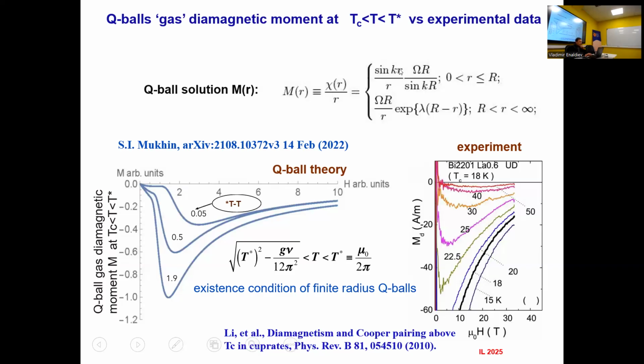How about coordinate dependence? Yes, indeed. If you do not substitute the Q-ball by a step-like function, but you minimize the effective free energy of the Euclidean action, taking into account coordinate dependence, then you get this solution. So it goes exponentially to zero outside the Q-ball, and it's nearly constant inside the Q-ball. And what determines lambda? Roughly speaking, lambda is of the order of the inverse correlation length of the fluctuation. This is very crude. In reality, it's not strictly so, but the details are here.